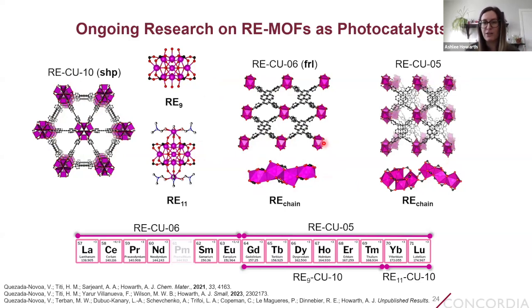Just as a side note, what's interesting about this is that Victor so far has only been able to make rare earth Cu10 with lanthanoids ranging from gadolinium to lutetium. And for rare earth Cu6, this topology and structure only forms when using the early lanthanoids from lanthanum to europium, whereas rare earth Cu5 forms when using the late lanthanoids from gadolinium to lutetium.